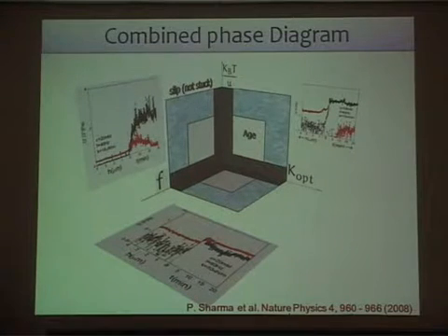So what I mean by never stuck to a plate is something which you see when you do experiments: you take a polystyrene particle, the particle comes to the plate, and it actually never leaves the plate, it's tethered to the plate. It just keeps on hovering about at that particular point. So if I calculate the G effective, the G double prime is mainly coupled through the viscosity. The tethered elasticity doesn't come out, except that it gives you a saturation in your mean square displacement versus time.